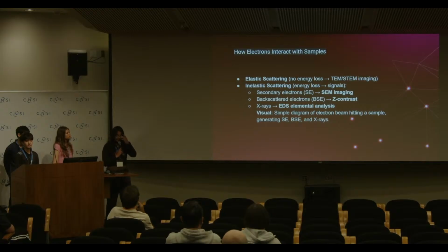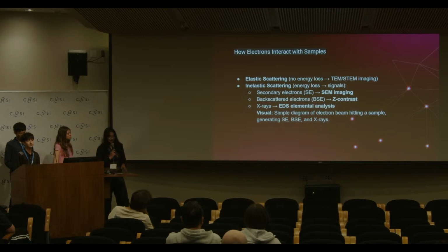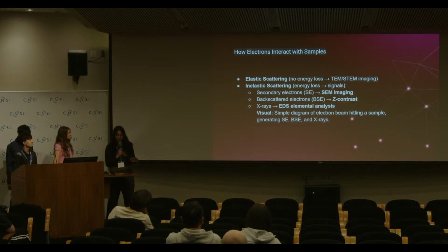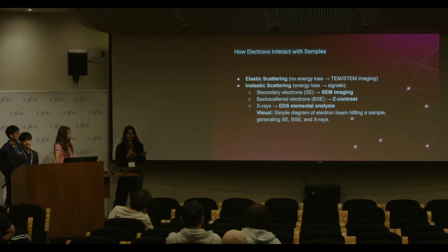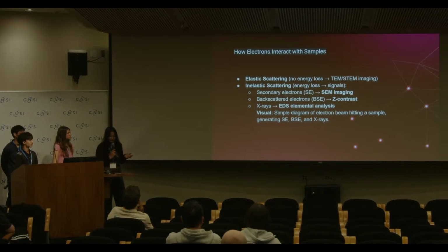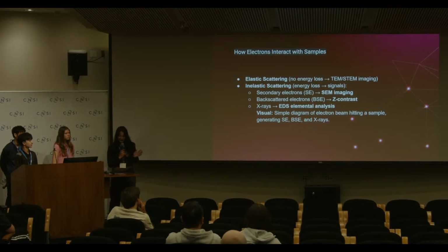The secondary electrons help us to see the surface topography. That's the standard SEM image. Backscattered electrons reveal composition and contrast, where the heavier elements appear brighter. And then the real magic actually happens with the X-rays, which is the basis of the EDS elemental analysis.